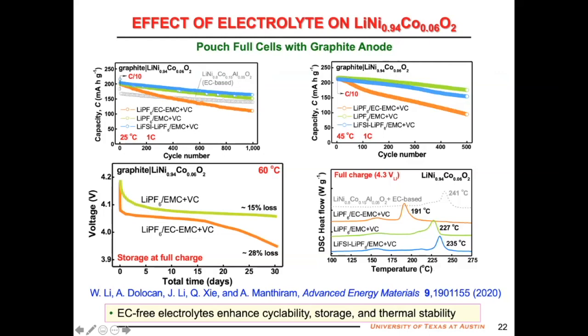When you do not have any ethylene carbonate in the electrolyte, that gives better cyclability, both at 25 degrees C as well as at 45 degrees C. It also gives better storage stability, the EC free. Not only that, when you remove EC, you also get better thermal stability. So conclusion, we cannot simply work with the cathode alone. We need to work on the cathode bulk, surface, as well as the electrolyte to have a good performance.